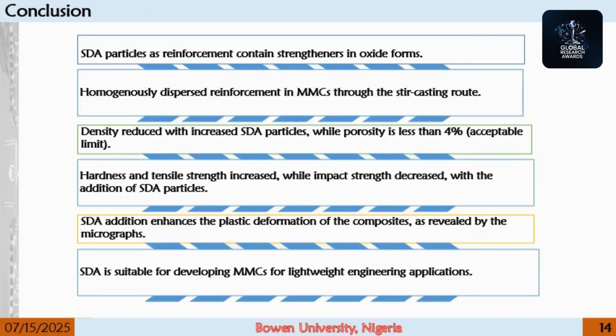In conclusion, this present study used environmental biomass waste derivative sawdust ash as reinforcement particles in aluminum 6063 alloy for the development of monolithic reinforced composite using the stir casting route. The structural, microstructural, and physical and mechanical properties of the developed matrix were investigated to determine the influence of SDA particles addition on the properties of the metal matrix composite developed. And from this, we could see that the SDA particles as reinforcement contain strengtheners in oxide forms, which strengthen the matrix when added. Homogeneous dispersion of reinforcements was achieved through the stir casting route, showing that the stir casting route is a reliable method of producing MMC.